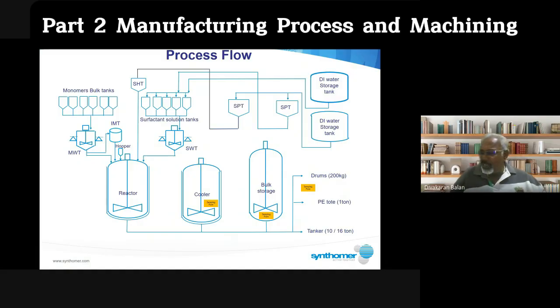After the reactor process for 9 to 12 hours, the product will transfer to the cooling tank. You see, beside is the cooling tank. The cooler is just a holding tank before you go to the storage tank, because in between, from cooler to storage tank, you will do the filtration. And the reactor, I forgot about this. In the reactor, we have a delay phase. So what is delay phase?